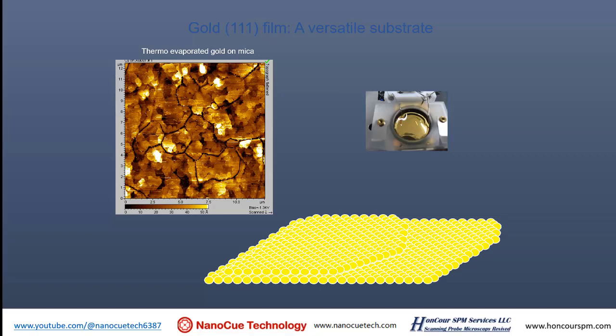You see the image in the upper left corner. How do you know it's clean? It's very hard to tell whether it's clean or not. But if you look carefully, there are steps somewhere, right? Now you measure the height of the step. It should be 2.35 angstroms. If it is 2.35 angstroms, then you know your surface is clean.